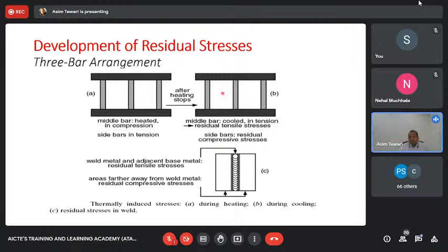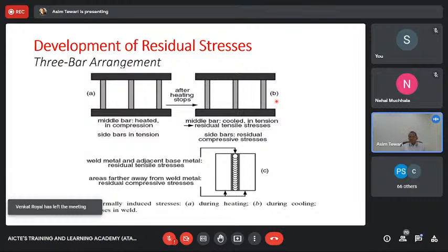Now remember, these two rods have also expanded because they were also heated up, but not to that large extent. So the expansion of the middle was the highest and the expansion of materials away from the middle was less. Now, the central rod being a liquid cannot sustain any stresses, so it loses all the stress and the liquid flows. And because the liquid flows and there are no stresses, the two rods on the side also then become without any stresses. So the entire stresses are lost the moment you get a liquid in the central rod. But we are not done with it yet.